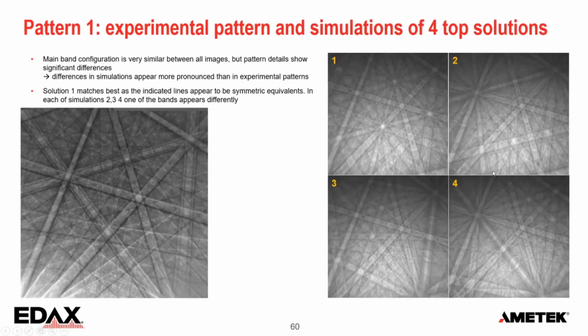So here's the first one. When I indexed this, I got four EBSD orientation solutions. Now, on the left is the experimental pattern, and on the right is a sequence of dynamic simulations. And when you look at this, you would say, how can you have a problem with that? These patterns look totally different. Now, there was one thing we noticed. The simulations were much more different than the actual patterns. So apparently, we didn't really get the atomic positions right. But even so, just look at the bands. If you look at this band here, and that one, those are in exactly the same orientation in all of these diffraction patterns.